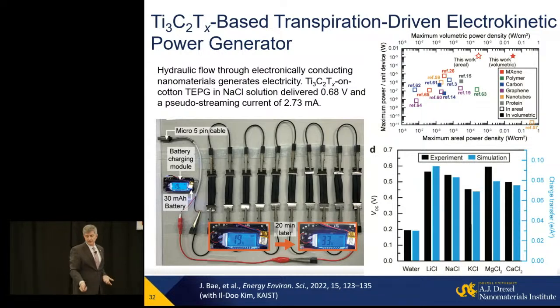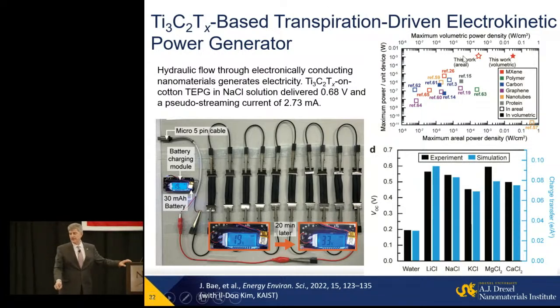It was shown on carbon, but the power generated was so small that it was absolutely impractical. Using hydrophilic and highly conducting MXene, where you get much lower resistive losses, we were able to go up 2-3 orders of magnitude in power density with this material, simply replacing carbon with MXene.